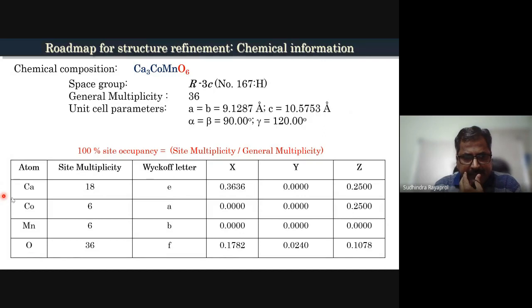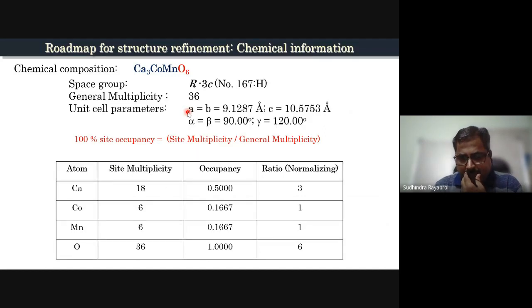And the reason for doing this exercise is that if you see the site multiplicity, it is 18, 6, 6, 36, which is basically a 3:1:1:6 ratio. So the occupancy which I have taken for this site, my 100% site occupancy is site multiplicity divided by the general multiplicity. So 18 by 36 is actually 0.5. But what it means is that this ratio of 18, 6, 6, 36 is basically 3:1:1:6. So my composition, if I take it in this format, will always be correct.